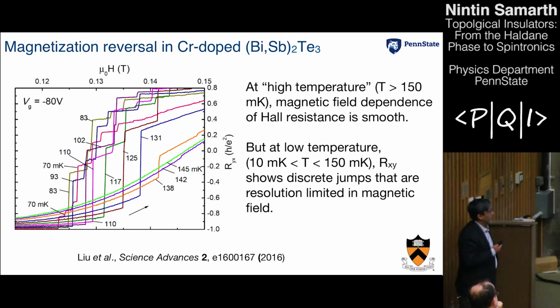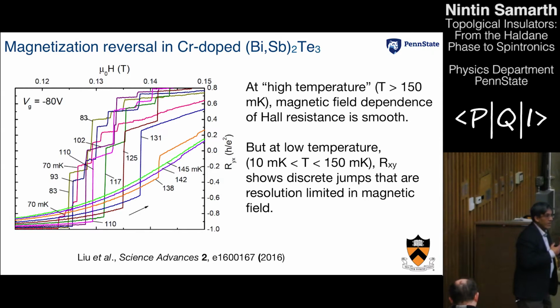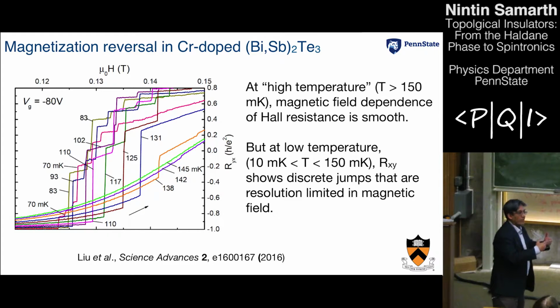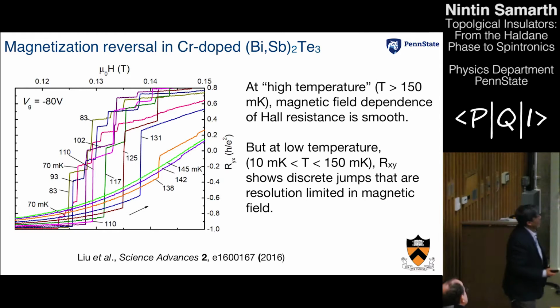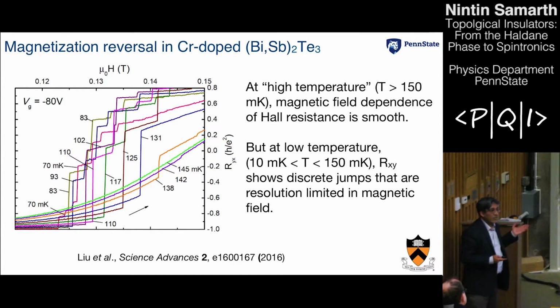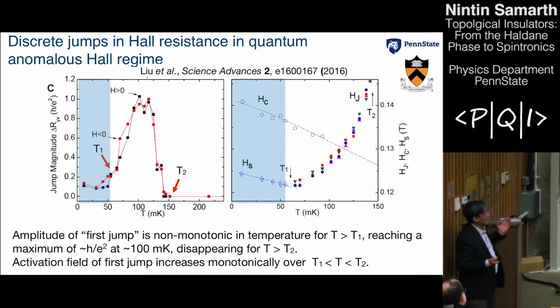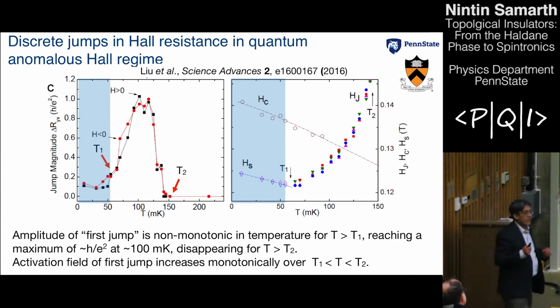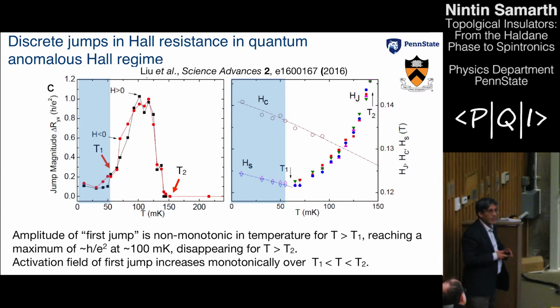We started wondering what this is due to. If you work in magnetics, the first thing that comes to mind is that this is possibly some kind of domain wall motion where you're getting domains that are pinned, and suddenly they get liberated, they jump, and then they get stuck in some minimum potential, then they jump again as you sweep your magnetic field. And as you raise your temperature, all this should be somehow thermally activated, right? So there should be a simple classical kind of explanation for this. But it turns out that that doesn't at all make sense. It does not jibe with what we measure experimentally.